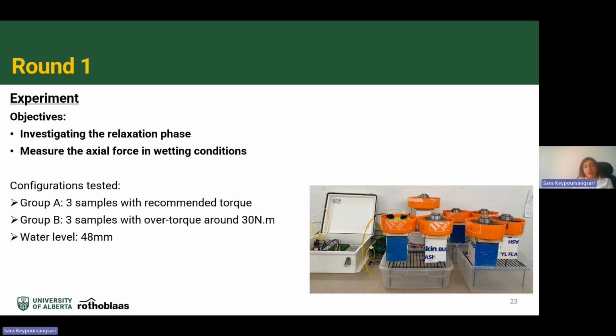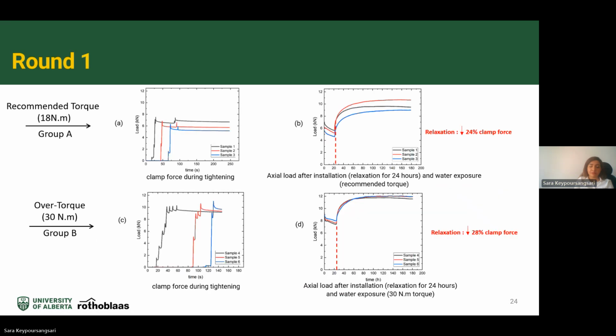In group A, 3 samples, self-tapping screws were installed with the recommended torque, and in group B, which was also 3 samples, they were installed with over-torquing, around 30 Newton meter. We also poured water inside this bucket to increase the moisture inside our samples. The level of water in this case was 48 millimeter, which was less than 2 lamellas. Here you can see the results of load, which was measured by the clamp force.